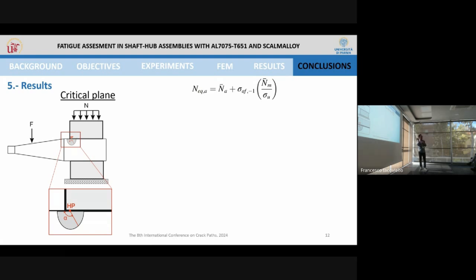For each material orientation, we are going to apply this expression. That basically depends on the amplitude of the normal stress to each plane, the mean normal stress to each plane, and the fatigue parameters, the fatigue limit, and the ultimate stress. Evaluating this expression for all the planes, the plane with the maximum value of this expression will give us the critical plane. Independently of the load applied, sorry, I forgot to say that we are averaging these values along a length of 2 times the grain size. Independently of the bending load applied, we always obtain a result between 5 and 6 degrees to the vertical.